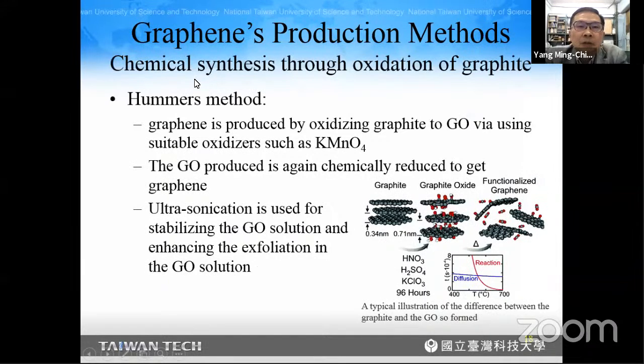The next method is the chemical synthesis through oxidation of graphite. In this category, the most common method is the Hummers method. In this method, graphene is produced by oxidizing graphite to graphite oxide by using a suitable oxidizer such as potassium permanganate. And the graphite oxide produced is again chemically reduced to get graphene.